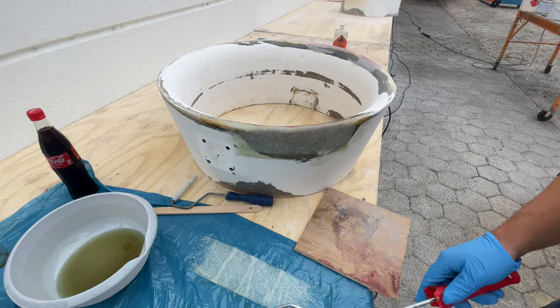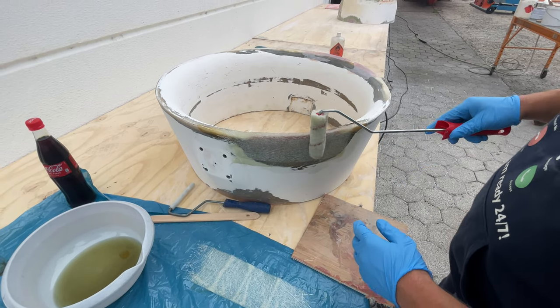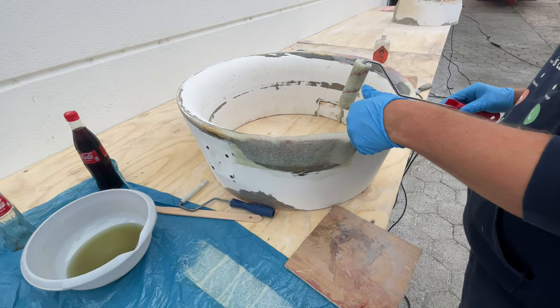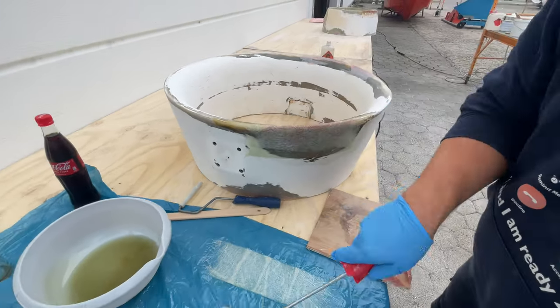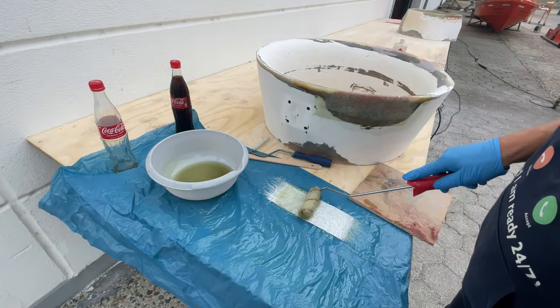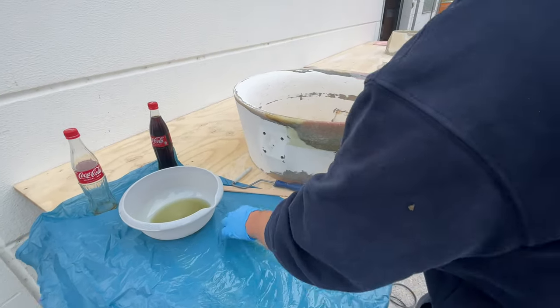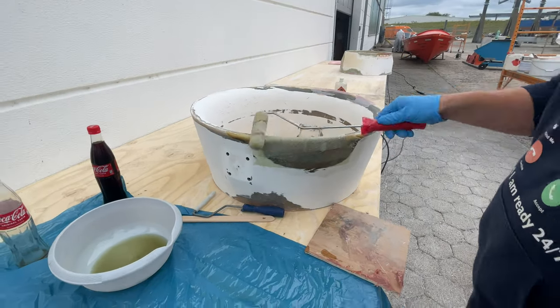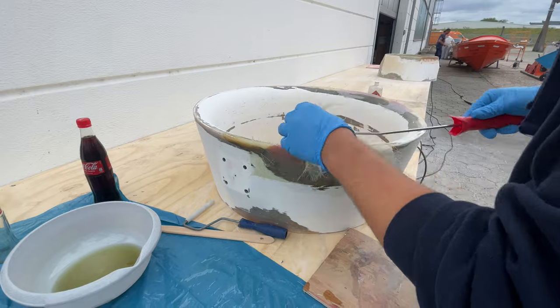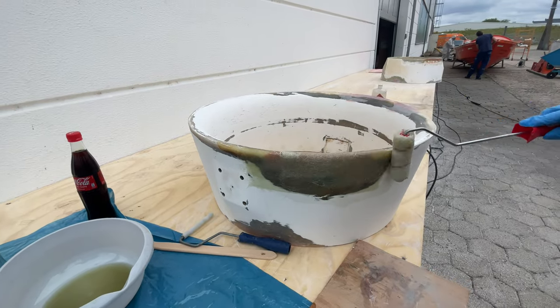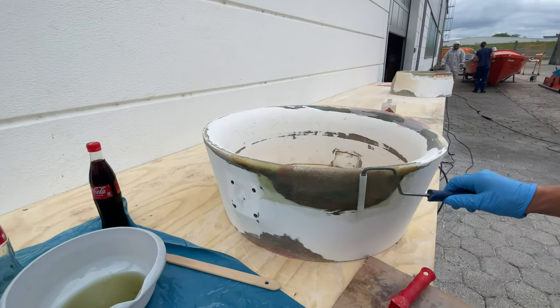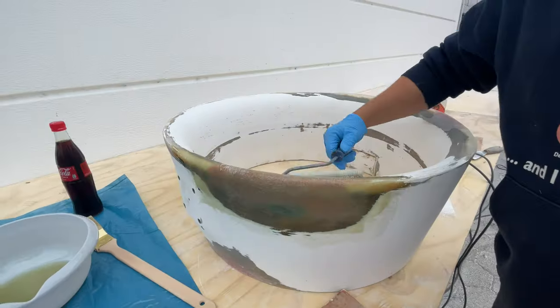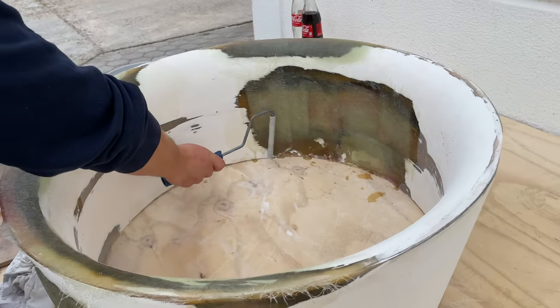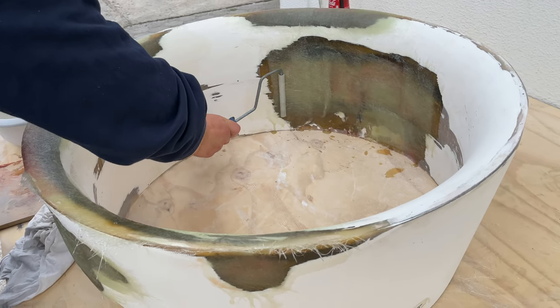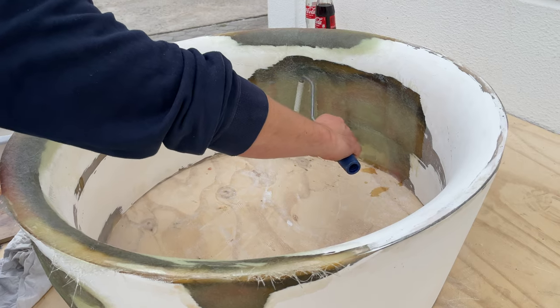Usually you can put up to 6 layers of glass mats on top of each other in one single step. After that, you'll probably want to wait until it hardened, then sand it down a bit and do another one so that it doesn't fall off. After putting on quite a bit of resin so that it hopefully doesn't drip down too much but is pretty soaked, you start rolling it with the laminating roller, or fin roller, I think is what some people call it, to get rid of any air bubbles in the material.